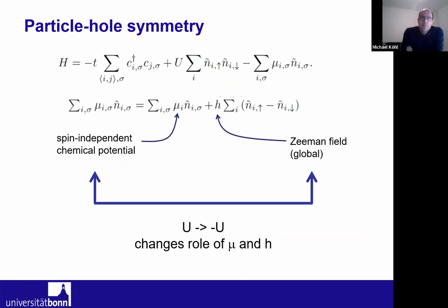So how this works is if we write down the Hubbard Hamiltonian and work in this particle hole transformation, then we see that it leads to a remarkable symmetry. Namely, if we change from attractive to repulsive interactions, the roles of the chemical potential and the Zeeman fields just flip. The Zeeman field measures basically the spin imbalance between the systems. It's called the Zeeman field because in solids, in order to have different chemical potentials for spin up and spin down, you would have to introduce a large magnetic field. In our case, with the ultracold atoms, we just throw in a few more spin up particles as compared to spin down particles. That's different, but it's still called a Zeeman field for historical reasons.